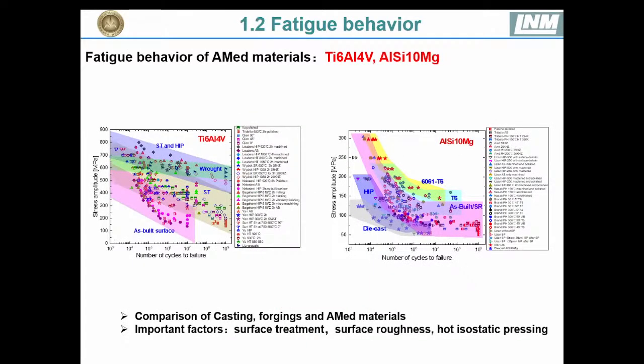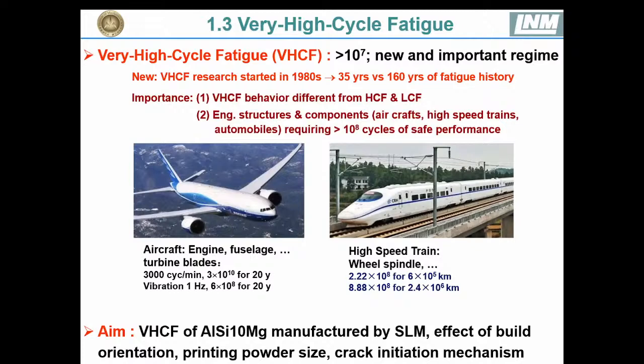And here, concerning fatigue analysis, our colleague collected some databases for two materials. One is titanium alloy, and the other one is aluminum alloy. In these two alloys, we can see that there are some factors affecting the fatigue behavior of these materials, such as surface treatment, surface roughness, and hot isostatic pressing, and also a comparison of the fatigue behavior of the cast and the printed material. Since there are a lot of important factors affecting this integrity, it is necessary to study some of the important factors and also to develop some models to predict fatigue life. That's the aim of our study, to study fatigue.